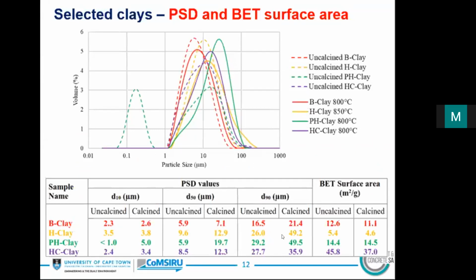Another parameter that we think is important is the BET surface area of the clay. In this case, the surface area of the clay, which also includes the internal surface area, was estimated using the Brunauer-Emmett-Teller equation based on nitrogen gas adsorbed on the surface of the clay using an instrument called TriStar. The good thing about this surface area is that it also gives you an idea of the internal surface area of the clay, especially if you have similar particle size distribution. It's clear here that HC clay has the highest internal surface area compared to other clays, and H clay has the lowest. So a mix with HC clay would demand more water or more SP, at a similar particle size, to get a similar workability.